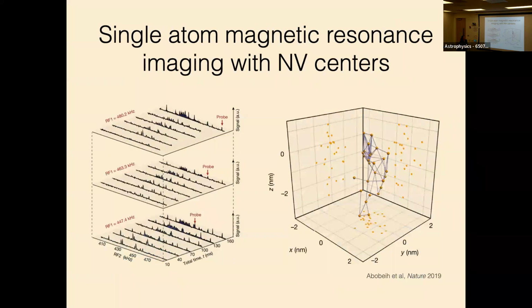Just to show you the power of the sensor, this is an example from Tim Taminiau's group at Delft from a few years ago, where they're looking at a single NV center deep in the diamond, and then they do these NMR pulse sequences to look at individual carbon-13 nuclei in the diamond. And they're able to really map out the positions of, I don't remember how many it is, but I think it's actually in the title of their Nature paper. It's like 27 carbon-13 nuclei. And you can see that they really have these positions all the way down to this deep sub-angstrom scale. So this is really incredible.